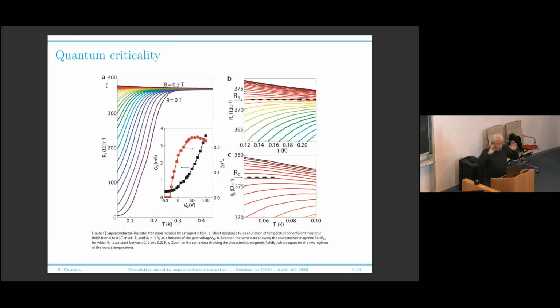Now, as a function of the magnetic field, if you look at the curves, there are two interesting regions. One region is around, say, 0.12 to 0.20 Kelvin, where you have a very flat curve at a certain value of your resistance, R cross. But then, if you go to even lower temperature and slightly larger magnetic field, you find another flat region with a larger value of the resistance and a larger value of the magnetic field. Now, how do you detect these two intriguing behaviors?